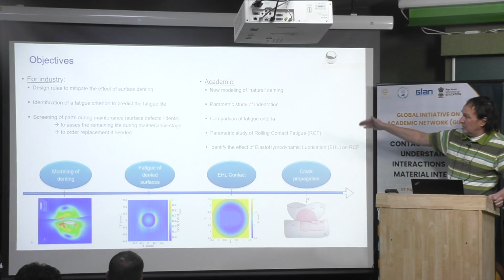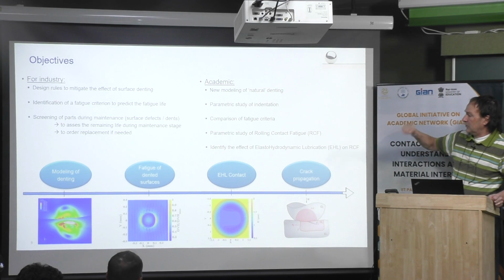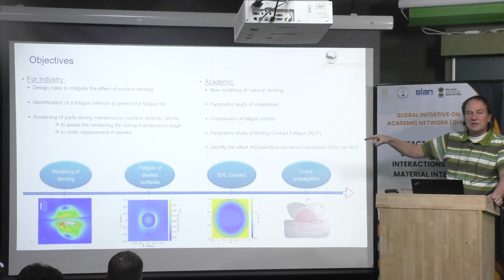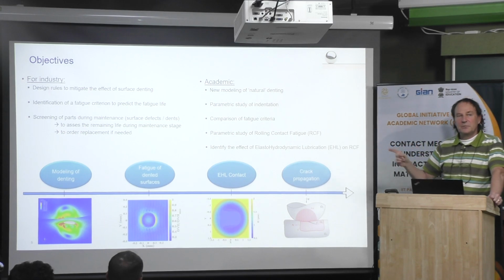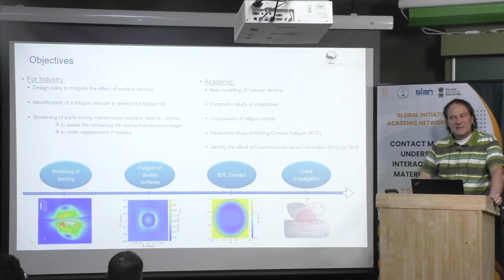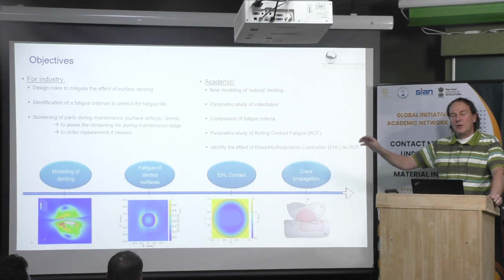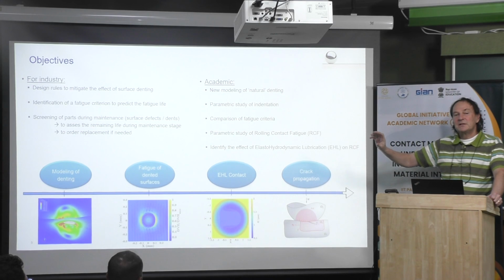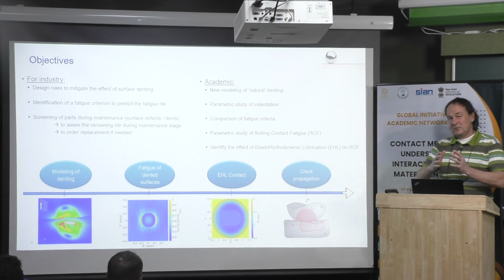And then for us, we develop a new model for debris denting, what I call natural denting. We are able to make a parametric study. The originality of the work for the finite element method is that we are using what we call the CEL approach, coupled Eulerian-Lagrangian model. In fact, the particle is described as Eulerian, like in fluid mechanics, because there is a lot of deformation. And when you have a lot of deformation with the finite element method, it's difficult. When you use a Lagrangian method, it crashes very quickly.